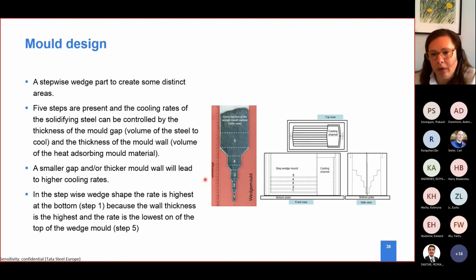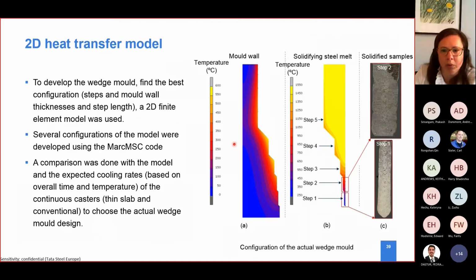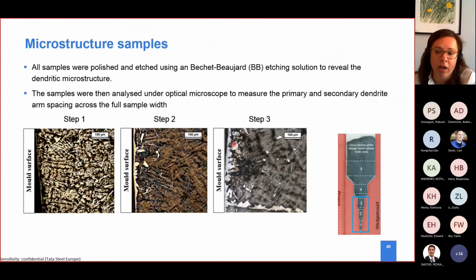Why? Because in one single sample, one time only, you have in step 5 and in step 3 the different casters. So step 3 will be very comparable to the thin slab caster, and step 5 to our slab casters. How we did it, we have done a very nice combination between a heat transfer model and this test and the analysis, moreover, of the microstructure itself. We also know the primary and secondary arm spacing of the dendrites. It's directly or indirectly related to the local solidification and the local cooling conditions. So in one step only, in one ingot, we can have all that information.